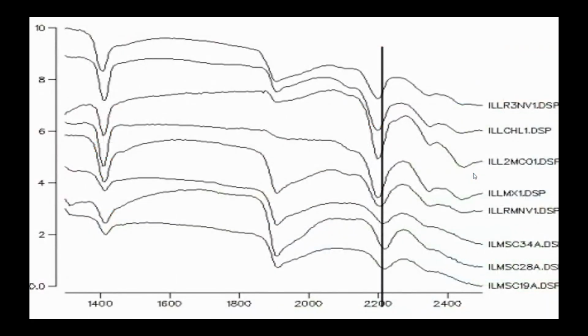So these are feature positions for a cross-section of muscovites and illites from the Speckman Mineral Library, ranging from 2198 nanometers to 2212 nanometers. So we're looking right here. And as you can see, if you follow along the line, you can see the shift as we go from illite to muscovite.